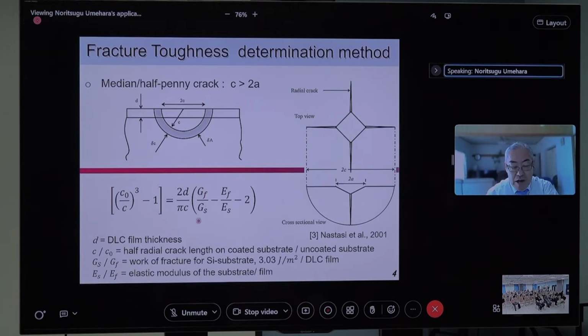GS is the work of fracture of the substrate. The substrate is silicon wafer. And then the elastic moduli, and C and C0. C0 is just for the silicon wafer, just for the substrate. And C is DLC on substrate. So in this equation, we know EF, ES, and also GS by another way.